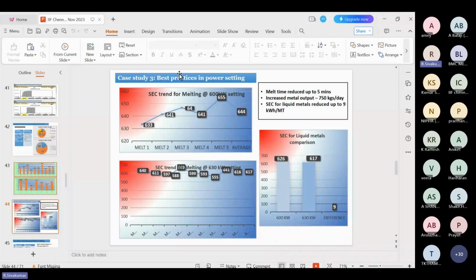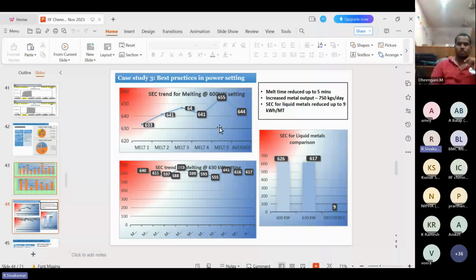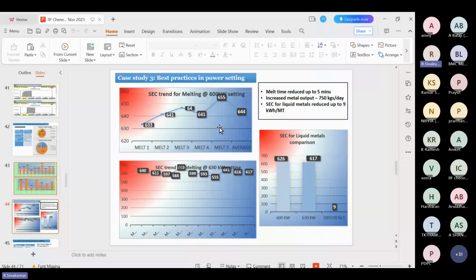Third one is power setting. This particular industry has a 750 kilowatt furnace with 1 ton crucible capacity. Due to the maximum demand availability, they are reducing the power to 600 kilowatt. They are not going above 600 kilowatt due to demand issues with the EB. During this audit, we did some auxiliary work also, so we informed the foundryman that you can give up to 50 kilowatt to the furnace, on the safer side 30 kilowatt. So finally the power setting is increased from 600 kilowatt to 630 kilowatt. The average consumption previously was 626 units. Now, after increasing by 30 kilowatt from 600 to 630 kilowatt, the average consumption is 617 units only. The melt timing is also reduced by up to 5 minutes.